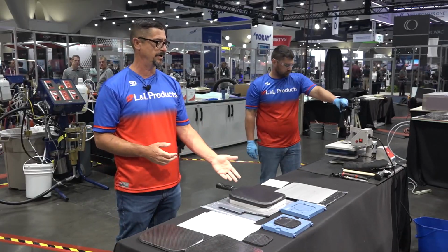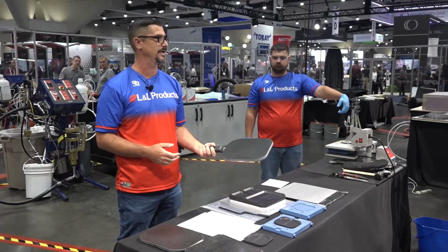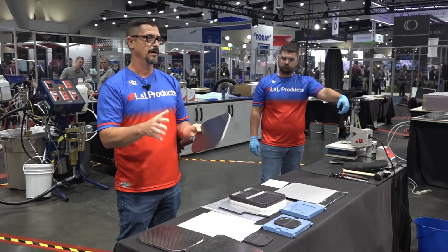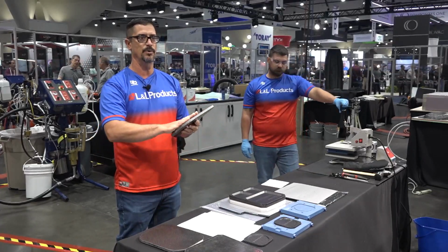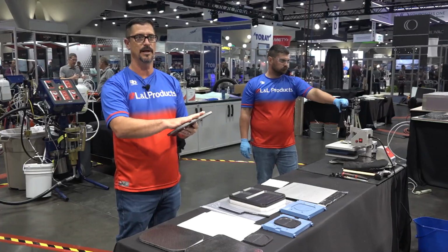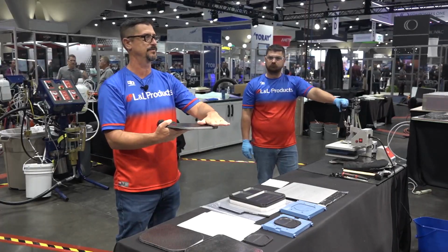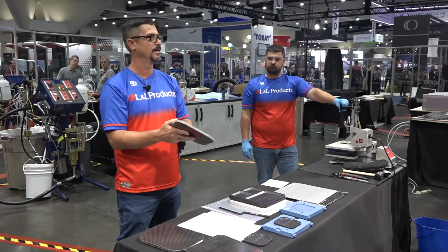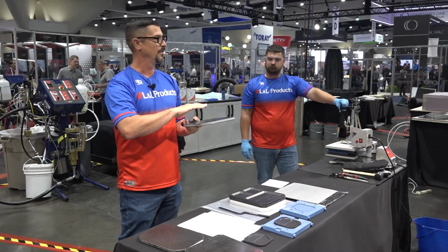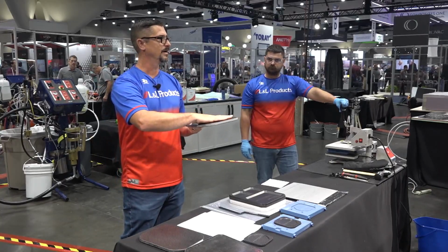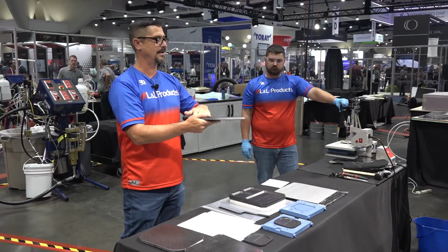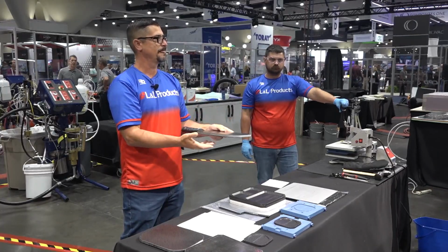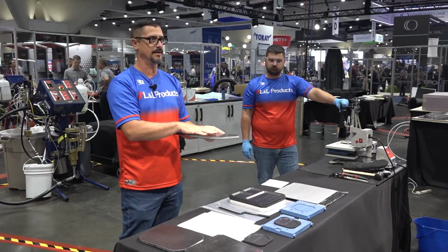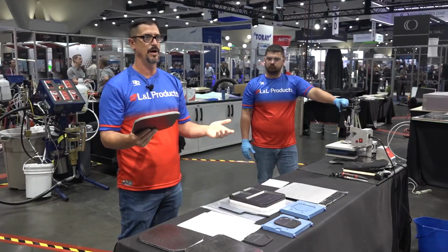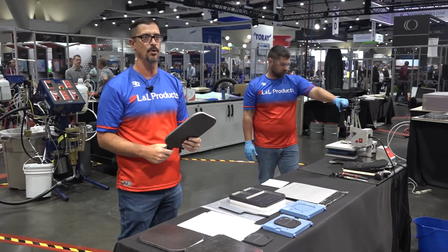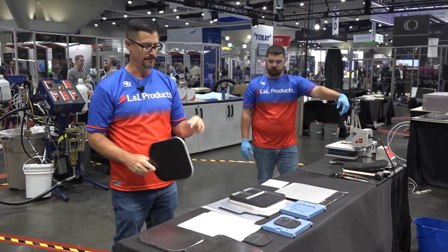So this material, like I mentioned earlier, is also an adhesive. So in the example where you may want to have an aluminum layer on one side and a glass fabric layer on the other side, we've made parts where we've had the aluminum on one side, dry glass fiber on the opposite side. Our material expands, wets out that glass, bonds to the aluminum. You have a finished part with a very low weight. You can have variable